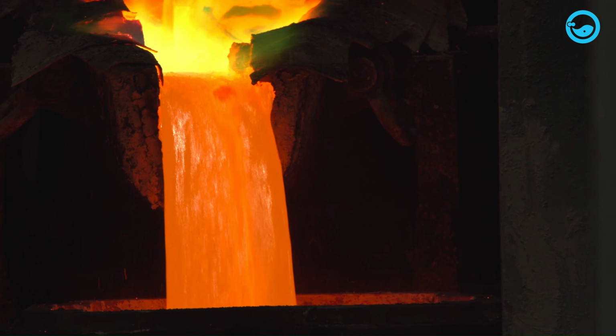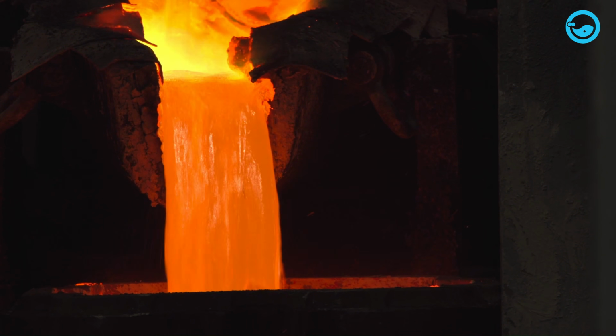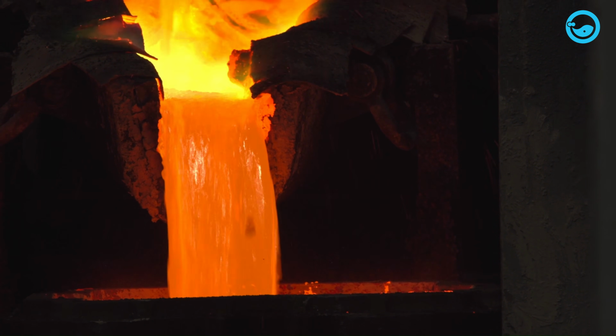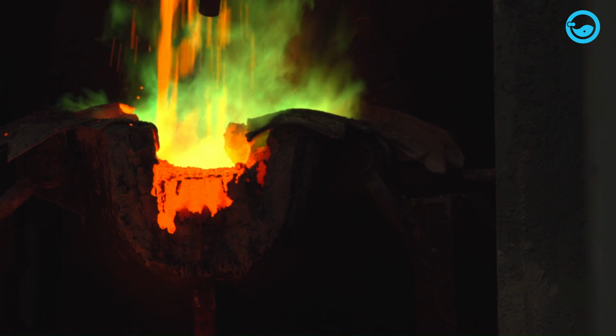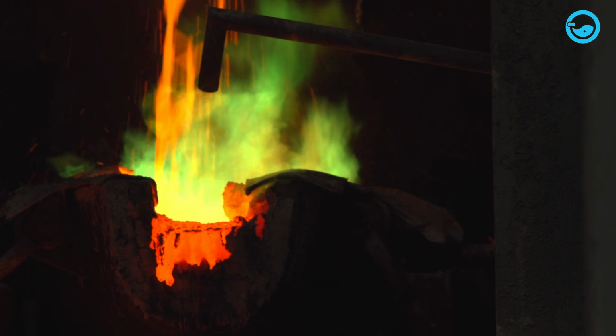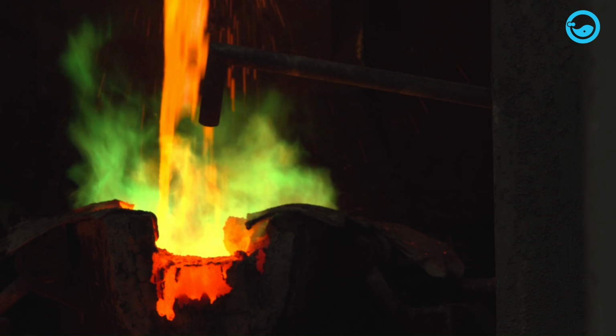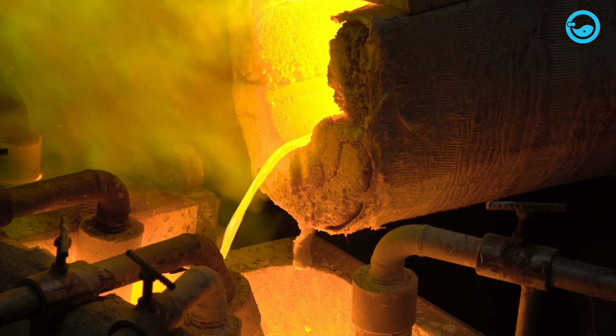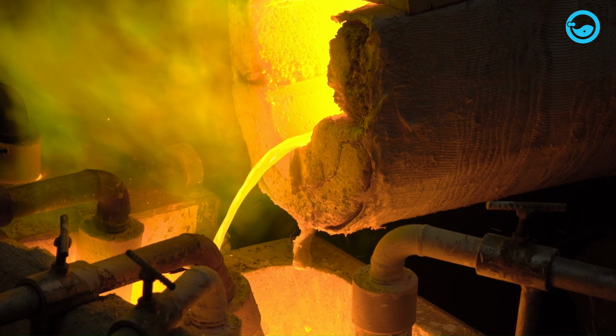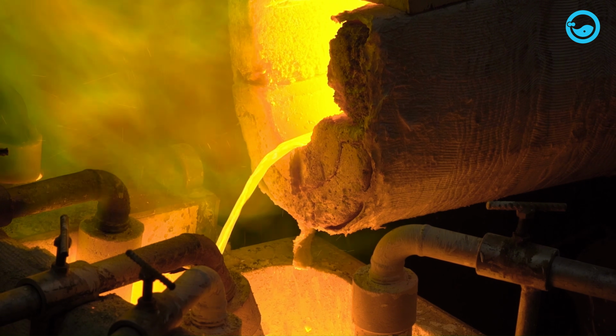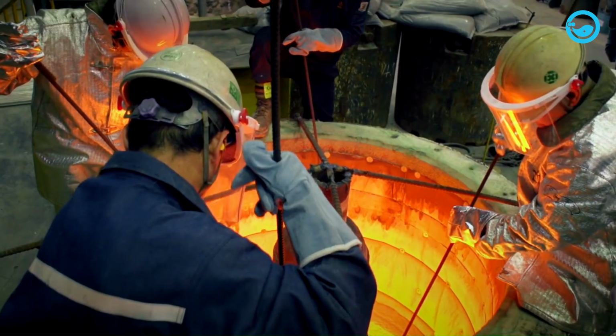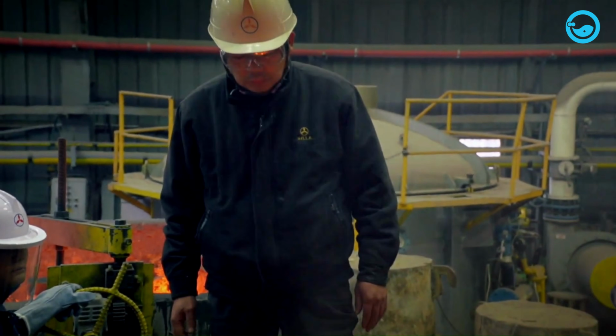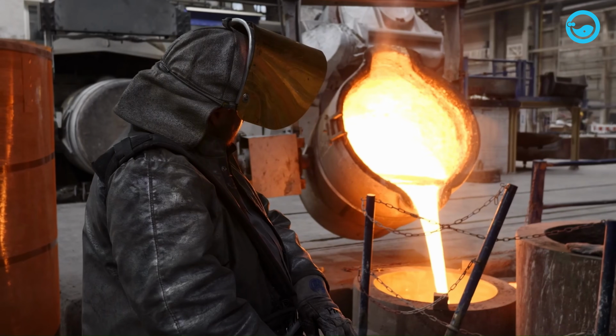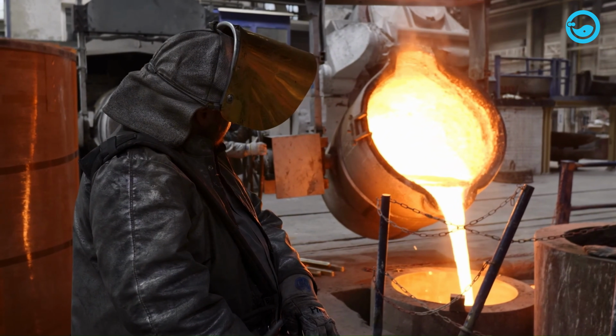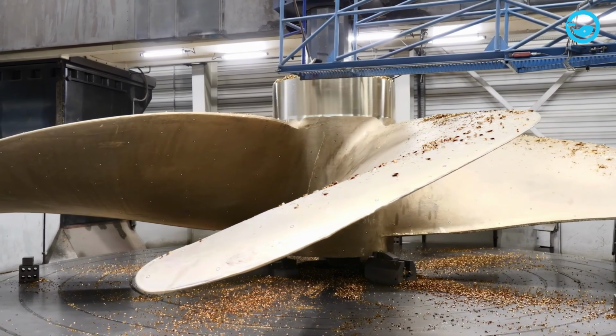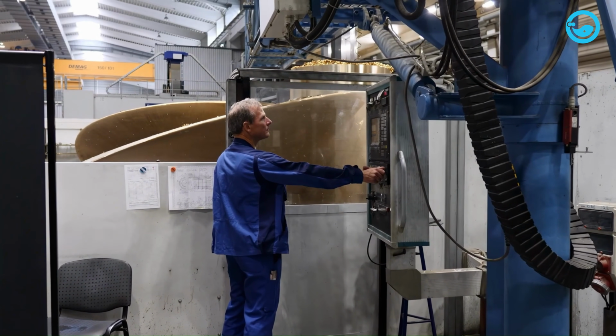The liquid metal is also degassed before it enters the mold. During the pour, the flow has to remain controlled. Turbulence can fold oxides into the metal or pull unwanted material into the casting. Foundry procedures use the runner system and slag control measures to keep the cavity filling as cleanly as possible. On the largest jobs, several furnaces or ladles may have to feed one pour in a coordinated sequence. The spectacular part lasts far less time than the preparation, but it creates the entire rough propeller in one operation.